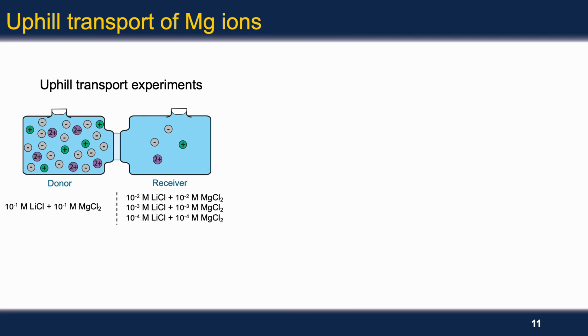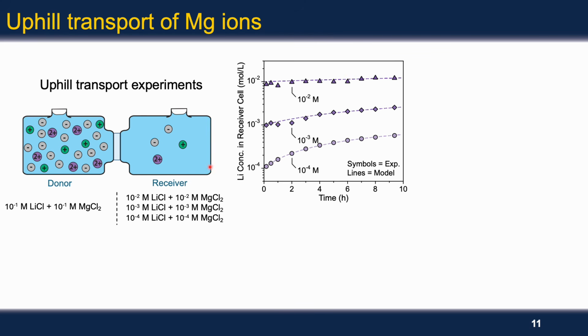To test the potential for uphill transport in our system, we performed a modified permeation experiment, where instead of starting with DI water in the receiver cell, we started with an equimolar lithium magnesium chloride mixture at a different total salt concentration. For lithium transport across the membrane, we saw that the lithium concentration in the receiver cell increased as a function of time, which is expected from normal Fickian diffusion.